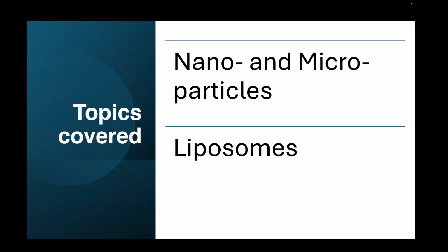Single emulsion method is basically a solvent evaporation method for mostly hydrophobic drugs, wherein there is an oil and water emulsion. So you put your drug in the polymer solution in the organic phase, and then use the water phase to create an emulsion, and let it stir to let the organic solvent evaporate, and that's how it will form your small particles.